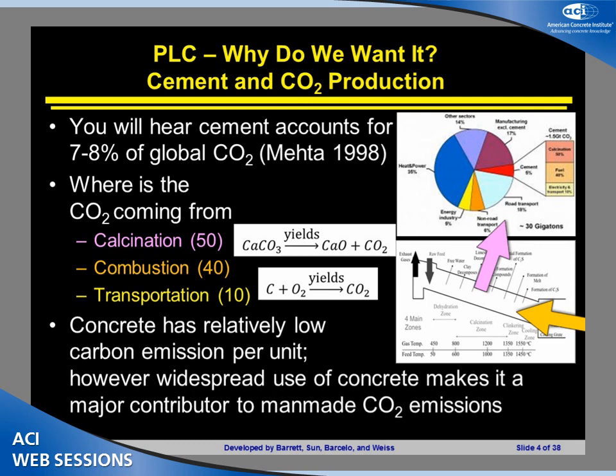You hear people talk about numbers as high as 7 or 8%. Here you see a pie chart where the numbers are about 5%. 5 to 8% of the world's CO2 production comes from the cement and concrete industry. And you may say, wow, that's a really high number. Cement must be awful. Well, one thing that we have to remember is concrete itself has a relatively low carbon emission, but the fact is we use an enormous amount of it. We use a lot more than we use any other material, and even though we have a low carbon emission, we're looking at ways to make this better because if we can reduce this number, that's good for everything.